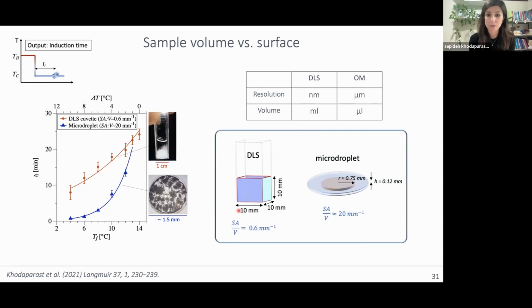than what you see in optical microscopy. The reason behind this is that the solid surface area relative to the volume of the sample is almost 30 times larger in the optical microscopy sample. So if I'm looking at samples like this and I don't wait 30 minutes, I might miss this crystallization temperature. It can be a similar thing in evaporation when I'm working with techniques like this.